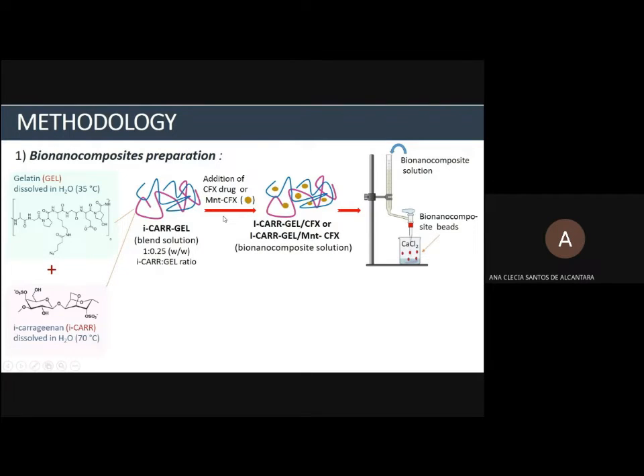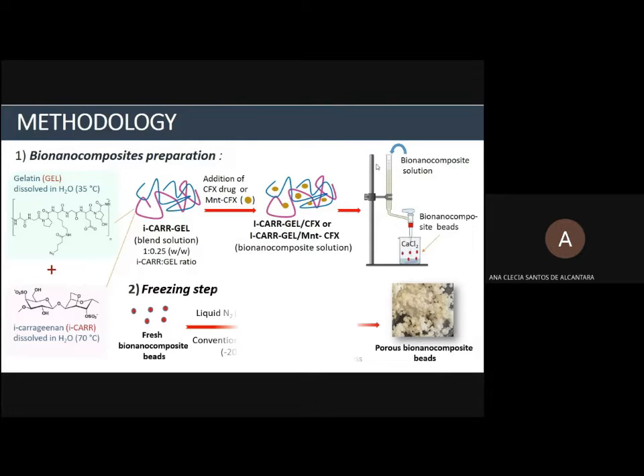In order to favor the cross-link process, the system is added dropwise into a 50% calcium chloride solution, obtaining in this case the bionanocomposite beads. These fresh bionanocomposite beads were separated in two parts. The first fraction was frozen by conventional freezing for 1 day, while the second one was frozen by immersing in liquid nitrogen, and both fractions were subsequently freeze dried, obtaining in this case the porous bionanocomposite beads.